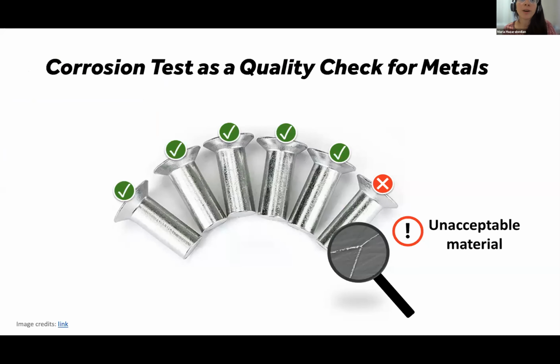Nickel alloys are one of the most reliable materials to extract oil and gas from aggressive environments due to their excellent mechanical and corrosion properties. However, specific batches had catastrophically failed, leading to important environmental damages and financial losses. The component cracked because of a ceramic precipitate that formed within the metal. The precipitate is only a few nanometers thick, and it was too small to be detected by the current qualification methods of the alloy. This is a big problem for the energy industry, as they don't have an approach to check the quality of the alloys they buy and guarantee that they are safe to use in service.